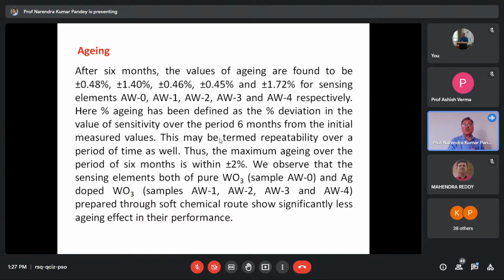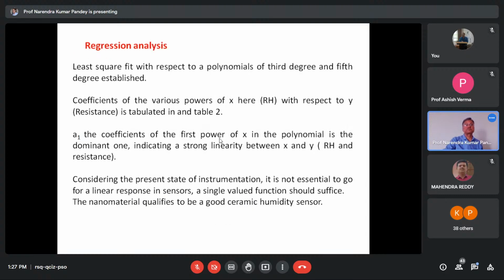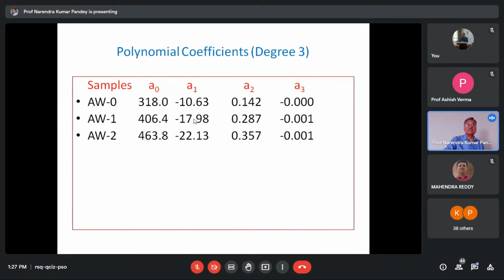That is, the sensor is able to be operated even after 4 months and 6 months. So this is repeatability over a period of time. The maximum aging for our samples over a period of 6 months is within plus minus 2%. Now, regression least square fit with respect to polynomial of third degree and fifth degree established coefficients of various powers of X with respect to Y, resistance, is tabulated. You can see if you are doing some polynomial or regression analysis, then the polynomial coefficients that we found were these ones.